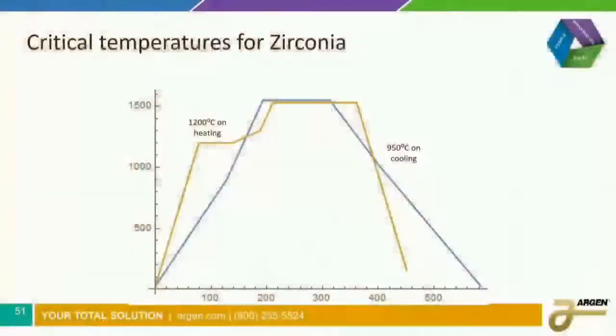Here's an example of two different recommendations for sintering monolithic zirconia. Here we have one that goes up at two different rates, holds it for 2 hours, and then comes down at a fairly slow rate. And here we have another one that's much more aggressive, but then they have a hold, and a little more complicated firing structure, again a hold at high temperature, about 1500, and then this one comes down a little faster. Okay? So what's the difference between these two? There's really no difference between these two with regard to the material. It's just how the particular manufacturer decided to present their case. Okay?